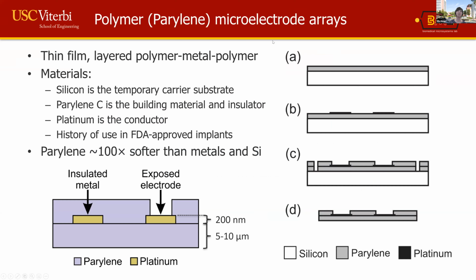And so here's a summary of the materials we use. I mentioned this very briefly earlier. We fabricate all of our devices on a silicon substrate. We use this because it's conveniently available. It comes very flat in a number of different sizes. And then we use Parylene C, which is a transparent polymer, as both the building material as well as the electrical insulator. And then platinum is the conductor that creates the sites for recording from different neurons, as well as allows us to make connections externally to the devices that are implanted.